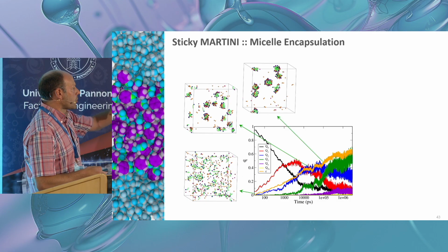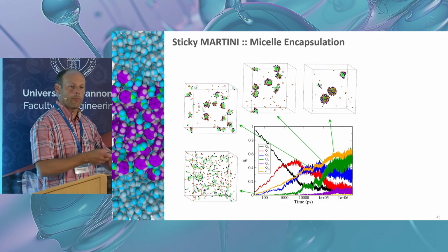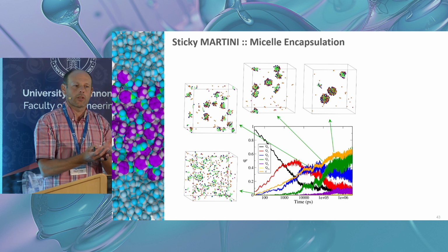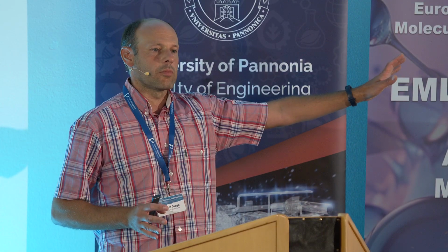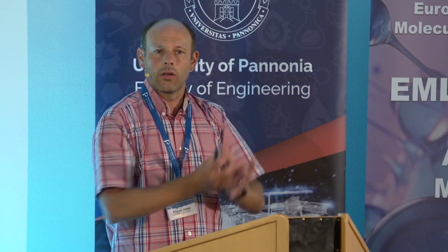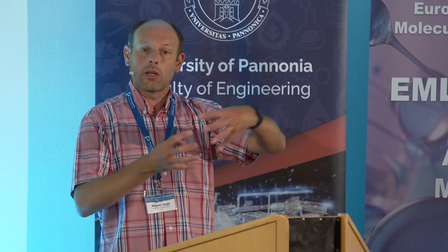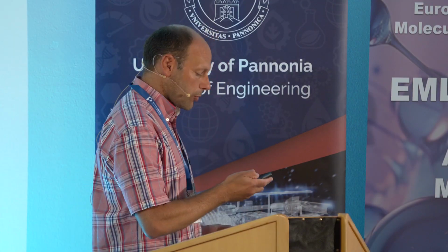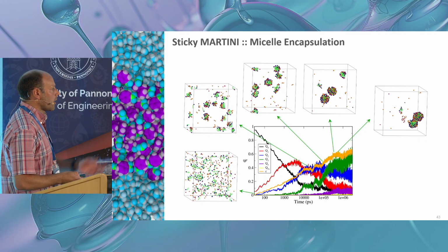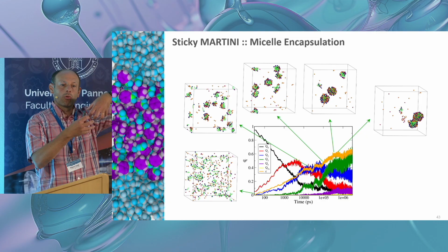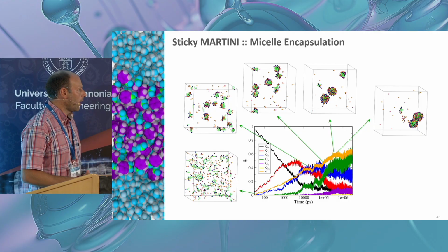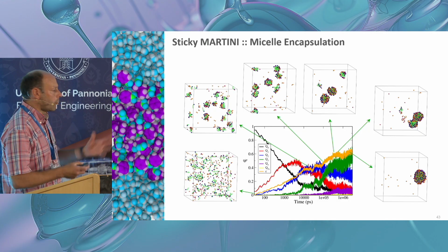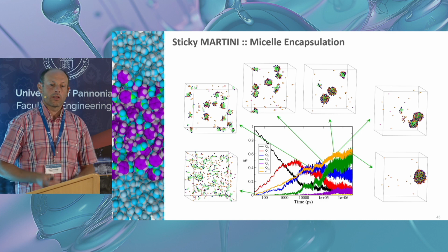So then these micelles grow, etc., and then you reach a point where you have protomicelles that are almost completely covered in silica, and I thought, okay, this is going to be the limit. It's not going to progress further than this because they are essentially frozen by the silica shell. But in reality, it's not. And that just shows that the reversibility of the silica reaction is key to this encapsulation process, because what happened was that as the micelles approached, the silica was able to open and accommodate the fusion of the 2 micelles. We followed that in real time, and it was really neat to see. And then eventually you form a single micelle, which is now coated with a nice layer of silica.